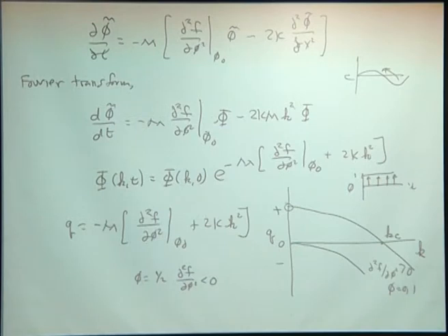Here, you just start off with a system of phi, and you can immediately change phi equals 1/2 to 1 by just doing it uniformly, just moving it up, right? And so you get the maximum amplification at q equals 0, because you can just move this whole system like that because it's non-conserved, okay?